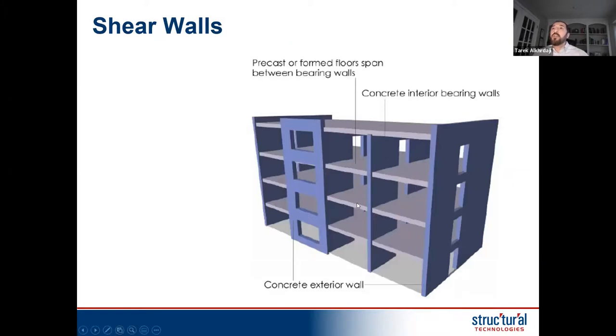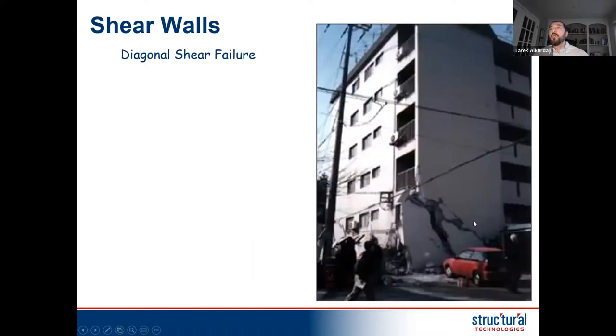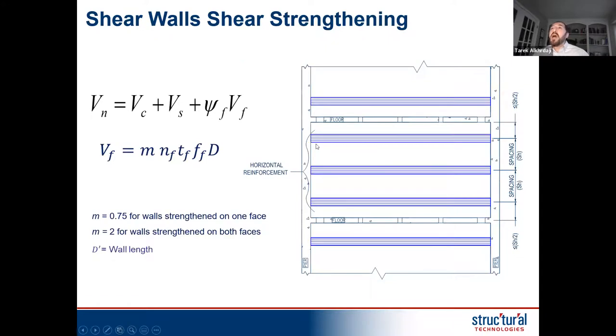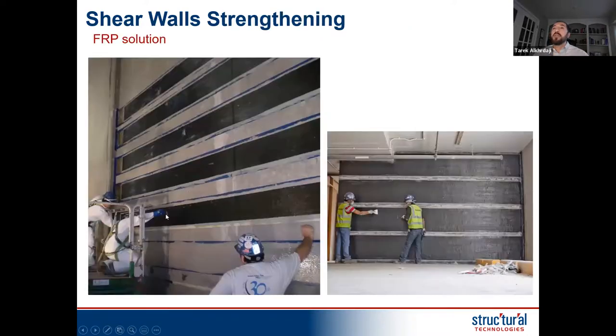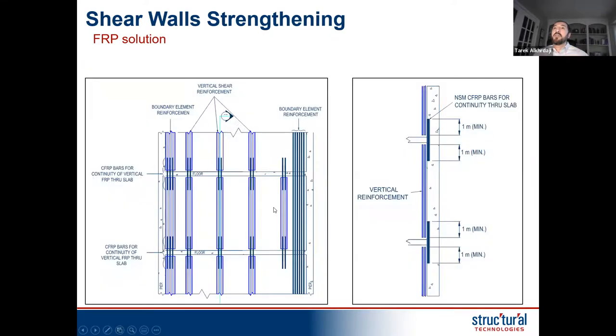And similar to shear in beams, there are shear walls. Shear walls can also, especially in existing lateral systems, become an issue in earthquake and maybe less severe in wind, but you still have to address these issues. I can use FRP as horizontal reinforcement. I can design them to take that additional shear force to increase the shear strength. So this is an example. This is one wall with FRP. And here is another wall with FRP, of course, different amount depending on the level of deficiency. And the idea is I mimic internal steel with externally bonded FRP to add that shear capacity that I need.